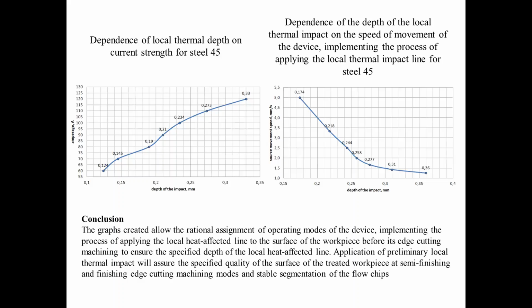Similar dependencies can be obtained for corrosion-resistant, heat-resistant, and alloyed steels and alloys with polymorphism, which are used to produce machine parts that operate in aggressive environments and have higher demands on the quality of their surface layers. The graphs created allow the rational assignment of operating modes of the device, implementing the process of applying the local heat-affected line to the surface of the workpiece before its edge-cutting machining, to ensure the specified depth of the local heat-affected line. Application of preliminary local thermal impact will assure the specified quality of the surface of the treated workpiece at semi-finishing and finishing edge-cutting machining modes and stable segmentation of the flow chip.